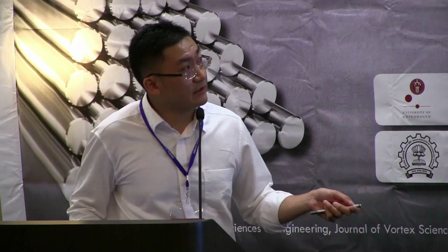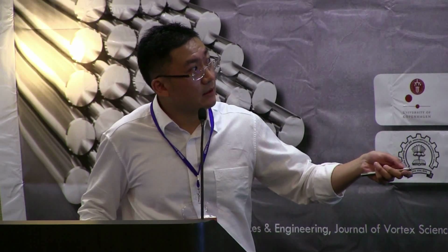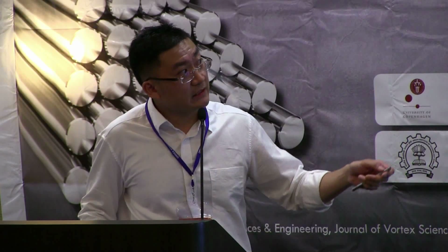So we look at the XRD, you can see the XRD follows the JCPDS card number here, and the peaks 111, 200, 220, 311 of platinum and palladium are very close. So basically, they are just 0.1 degree angle apart. But if you look at the high resolution here, I would say the platinum is around 39 and palladium is around 40. So we change the different ratio, we form the alloy, and the peak is within the range. So that means we have the alloy conditions.